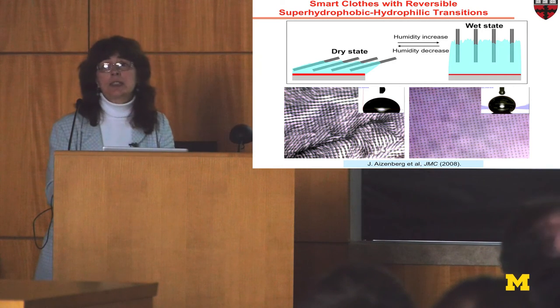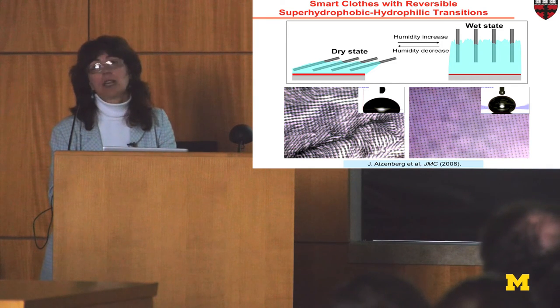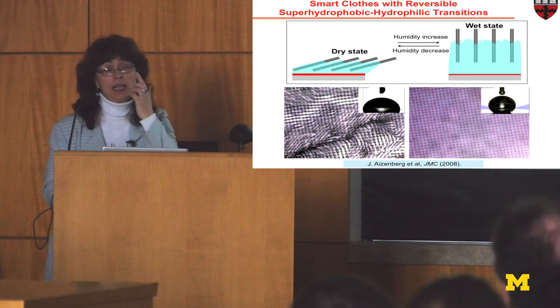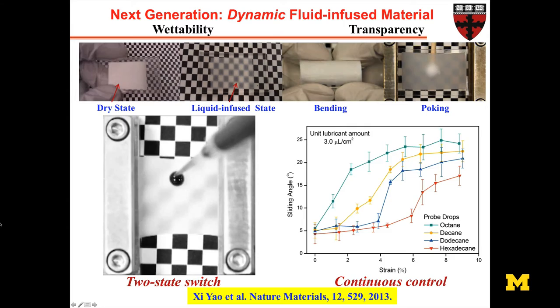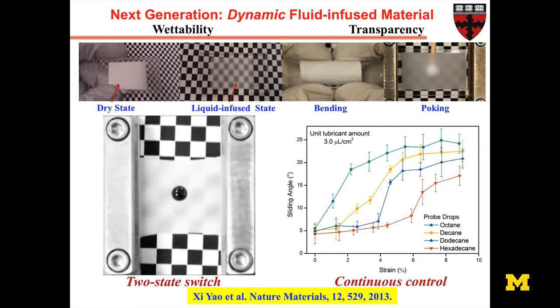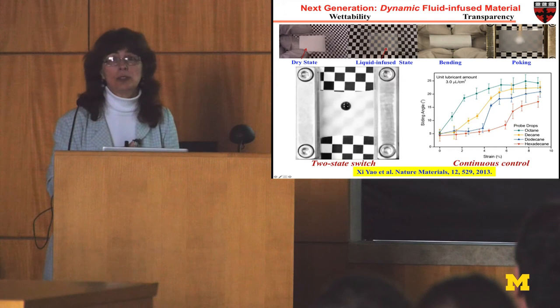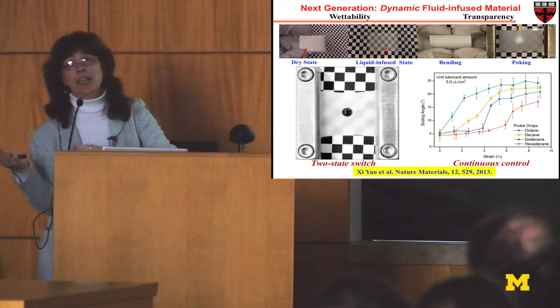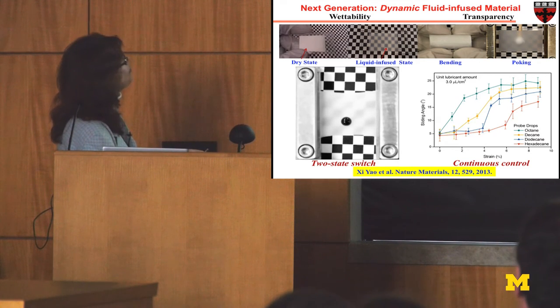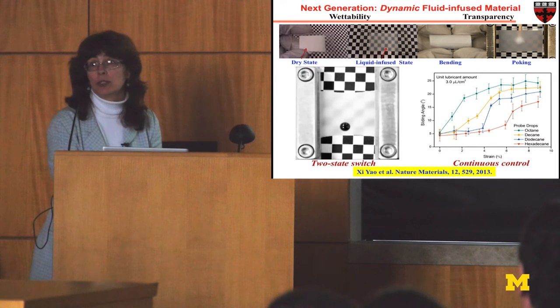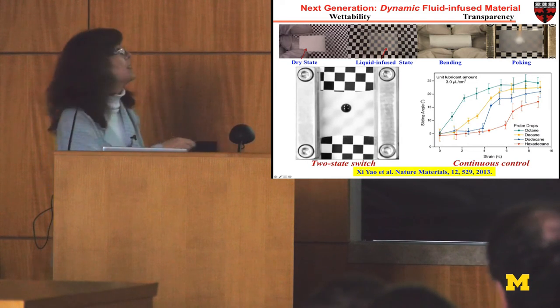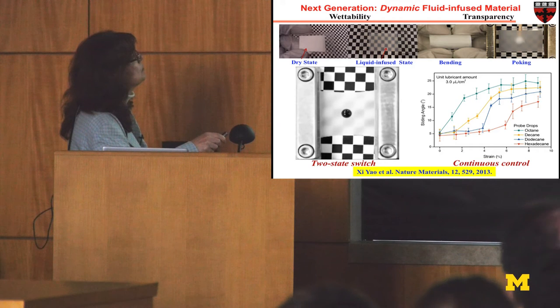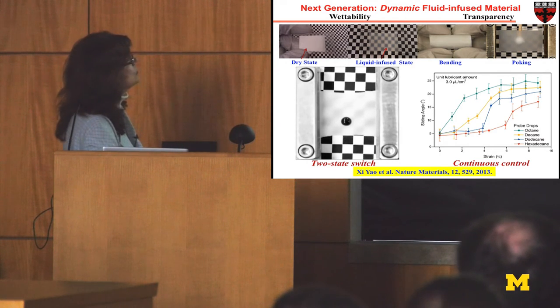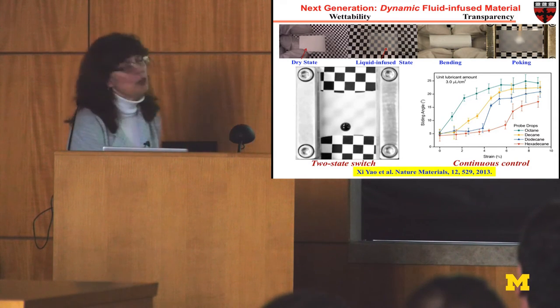Or let's go even further, and I was talking about slippery surfaces that instead of air would have a certain liquid inside your structured surface. But you can do a lot of interesting tricks if you think about it in a dynamic fashion. So since the liquid inside your surface is related to the available volume inside the structured material, I can use reconfigurable materials, could be porous or structured, where the material is lying down or standing up. And in this way, the top liquid is either withdrawn back into the structured material and becomes sticky, or, depending on strain in this case, it will come back and the droplets can either be stopped, and you could see that you stretch it, or when it stops, you release it, it continues to go without staining the surface.